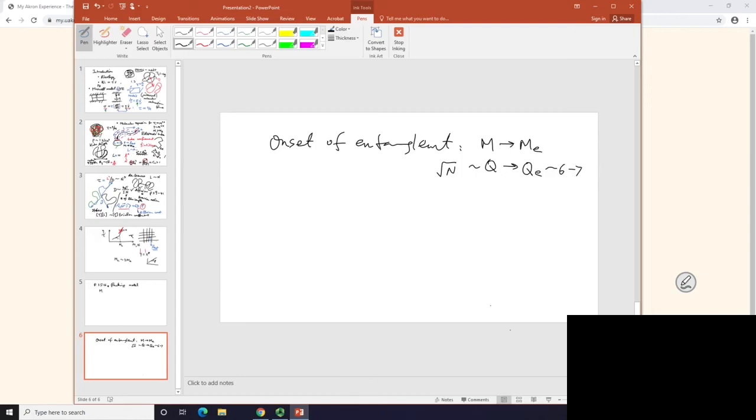In other words, if I have 6 or 7 chains in my own volume, that's about the place beyond which I start to see other chains interfering with me. And the magic is this number, 6 to 7, is the same for all different polymers. That's the most powerful part, which you can accept. Who cares if it's polystyrene or polyethylene? As long as I see myself being surrounded by 6 chains, you are getting to a point where I'm not comfortable anymore. I cannot move much anymore. The only way I can move is through a tube now.